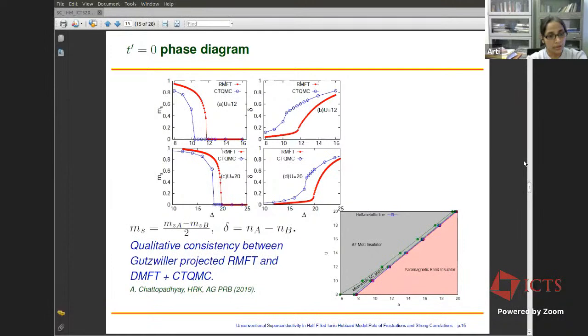And in the absence of next neighbor hopping, this is the phase diagram that we obtain: there is a transition from a band insulator with the dominant charge density wave order to the Mott insulator with the antiferromagnetic phase order. There is a very thin half antiferromagnetic half metallic phase in between, and if one forcefully suppresses the antiferromagnetic order, then one can see a thin metastable superconducting phase as well in this limit.